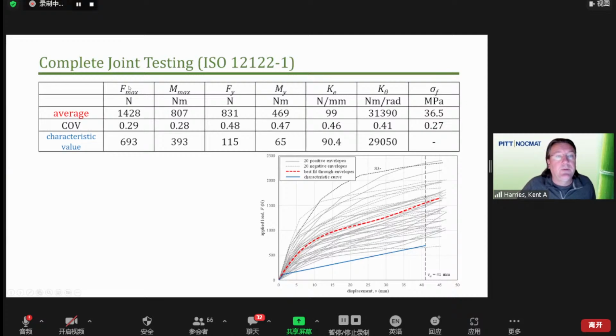We look at both our applied forces and moments, so F max and M max, yield, Fy and My, stiffness, so Ke is the observed stiffness, the load versus displacement, K theta, the rotational stiffness, and then finally the extreme fiber stress, which I'll come to in a second. We can look at their averages, we can look at their coefficients of variation, and we notice as we normalize the data, we get a small improvement in each case, as we'd expect, because we're normalizing out the effect of culm diameter and wall thickness. And then we determine our characteristic value.